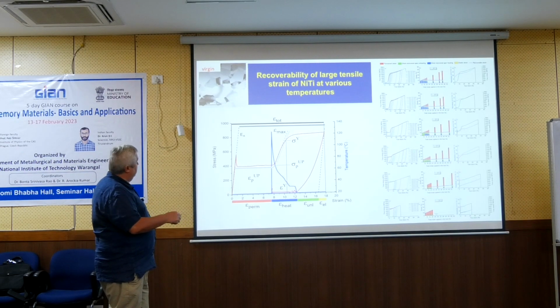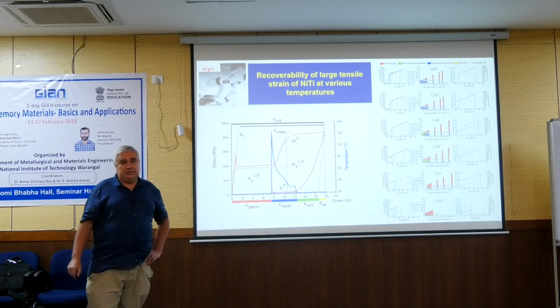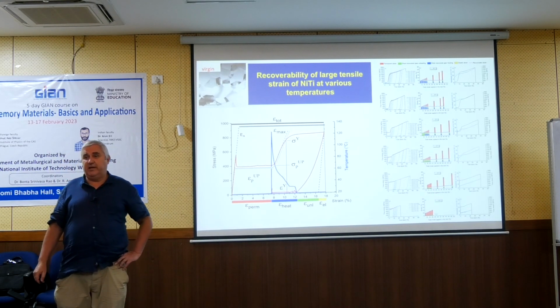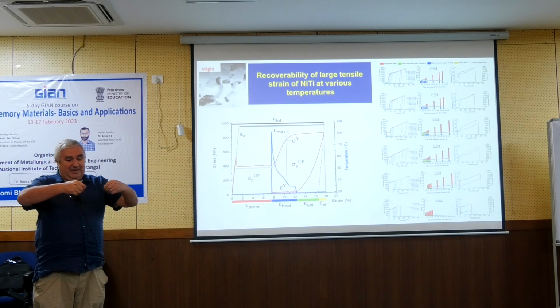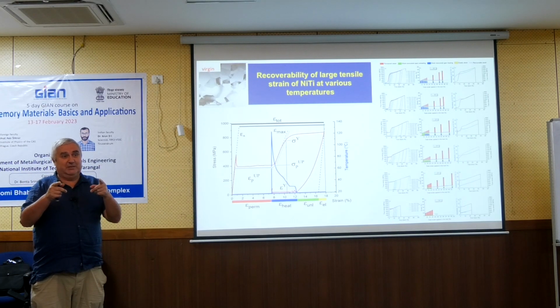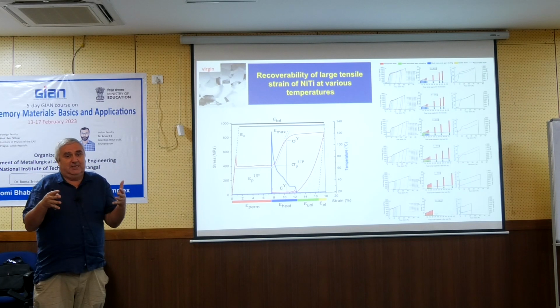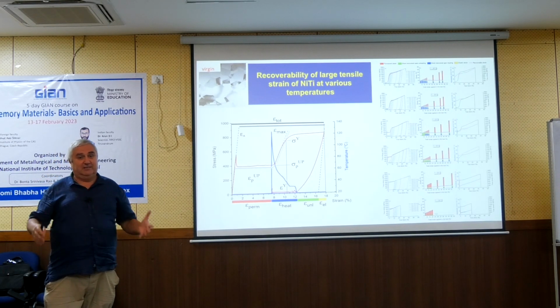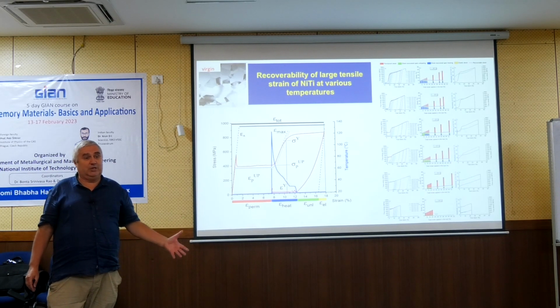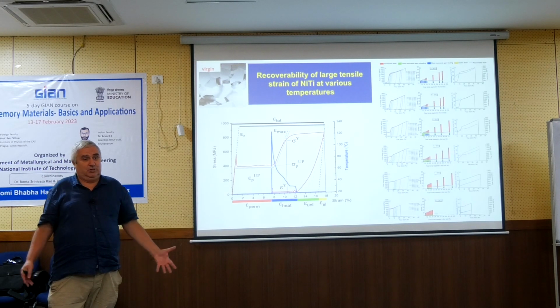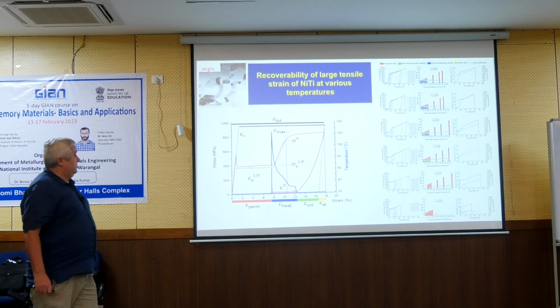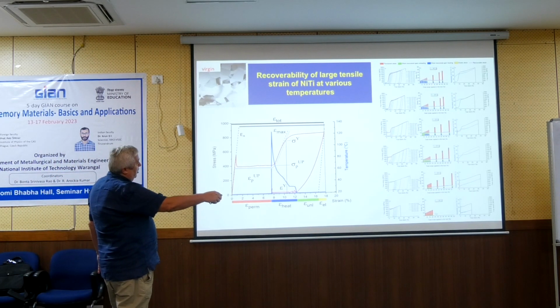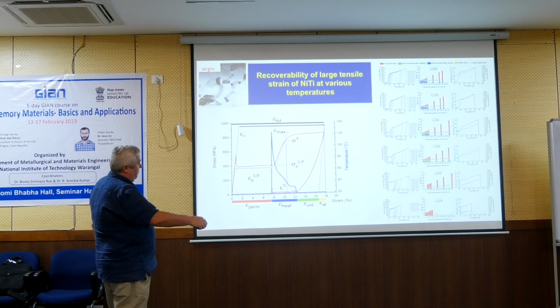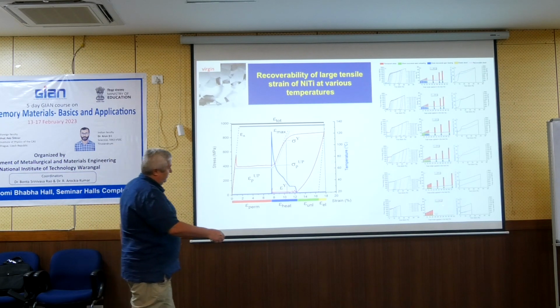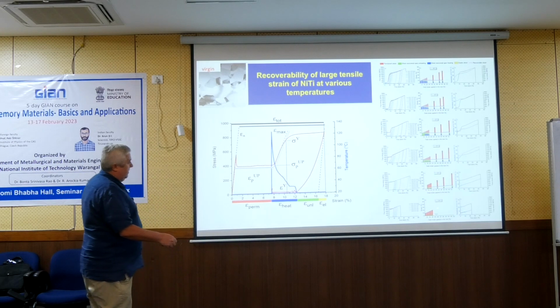Red is permanent. But even if you load the wire up to 20, 30, 40, you still have 10% recoverable strain. I was not aware of that, but the wire deforms plastically, and still the recoverable strain, on unloading plus on heating, remains 10%. This is very difficult to understand, because if the deformation occurs by plastic deformation, this should not really happen. The question will be why this 10% remains. It is the case for low temperatures, but it is not really the case for very high temperatures like 150. Most of the strains are permanent, not recoverable.